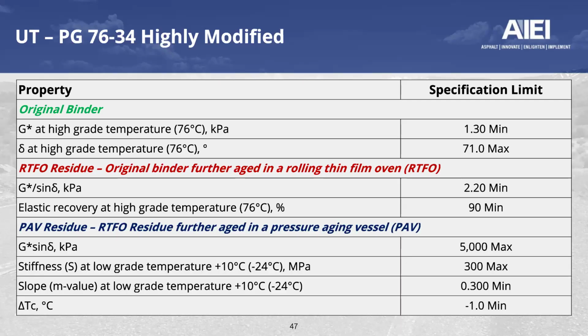After it runs through the rolling thin film oven to simulate what may happen at the hot plant, you can see they have some typical requirements, including an elastic recovery conducted at 76 degrees of a minimum of 90% recovery. They continue on with your typical PAV requirements to simulate some longer term aging in the field. And the one of note that we like to point to that is a little bit unique in the state of Utah, but not exclusively, is looking at a Delta Tc, where they have a requirement of a minimum of -1.